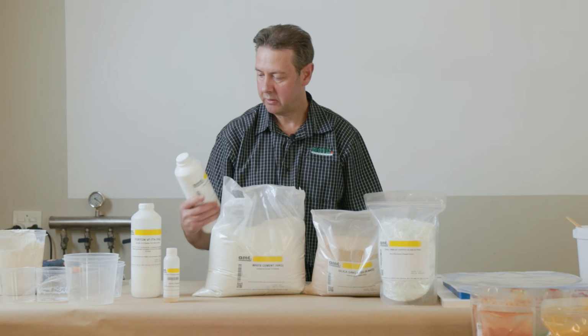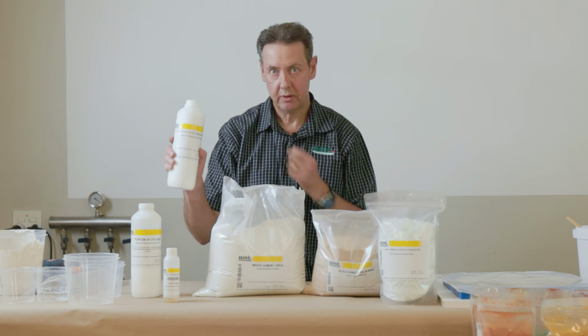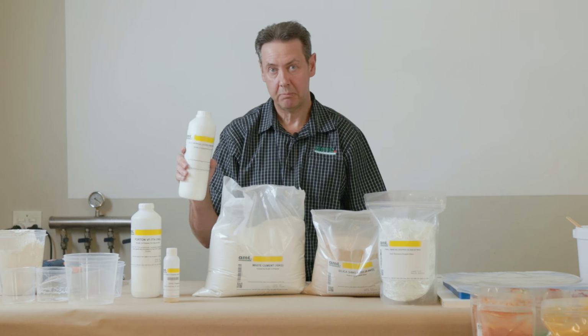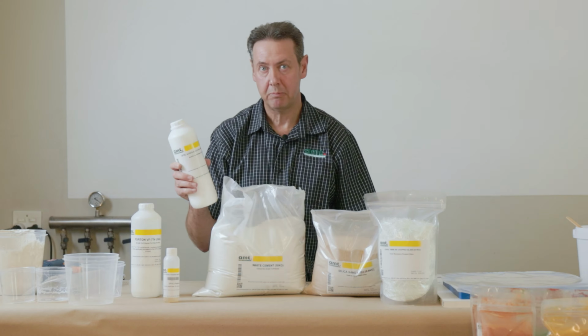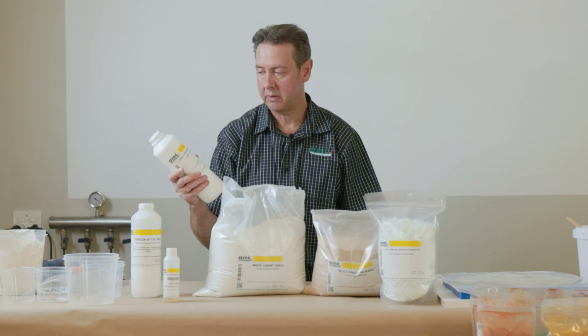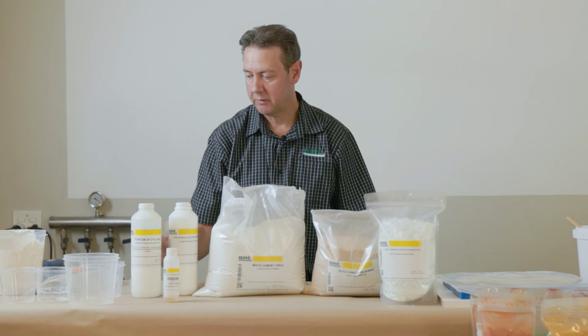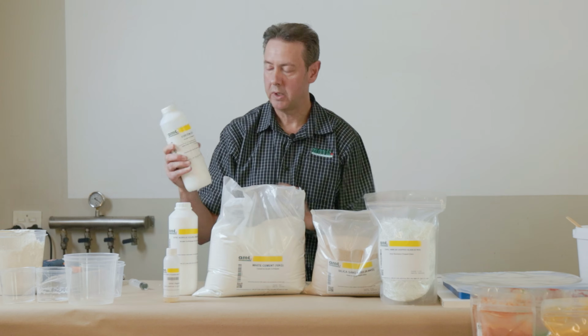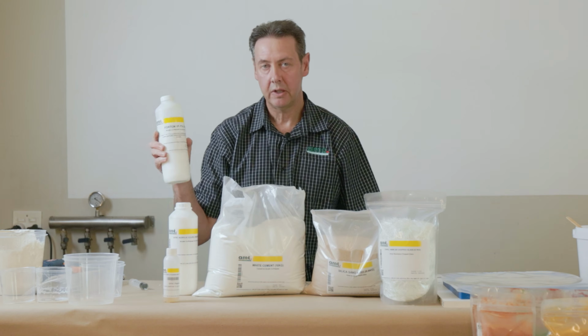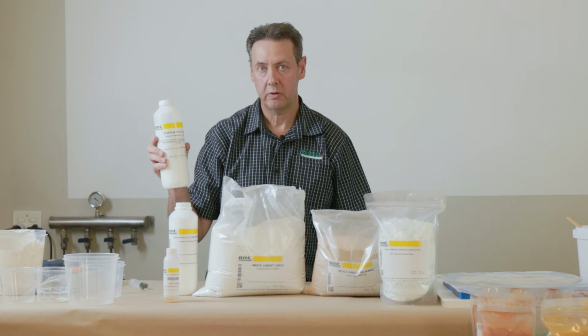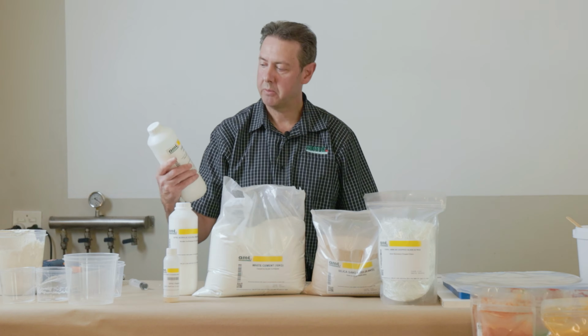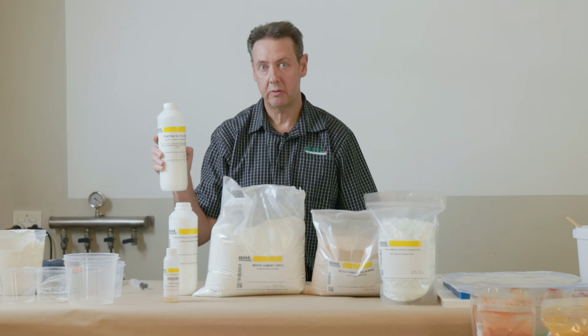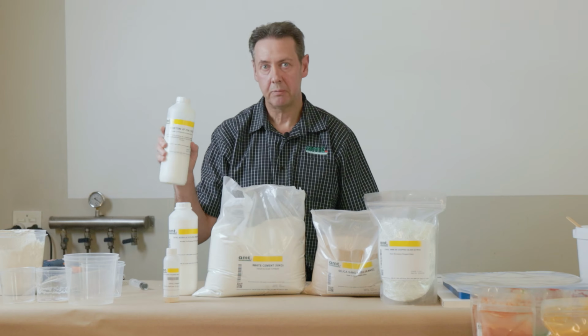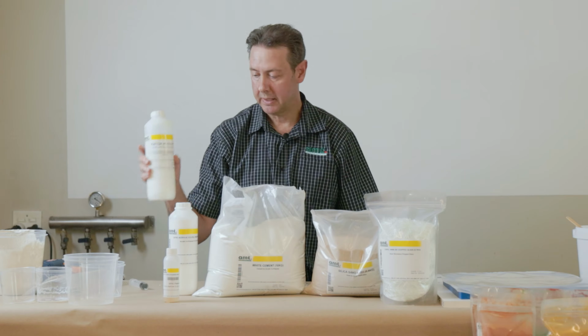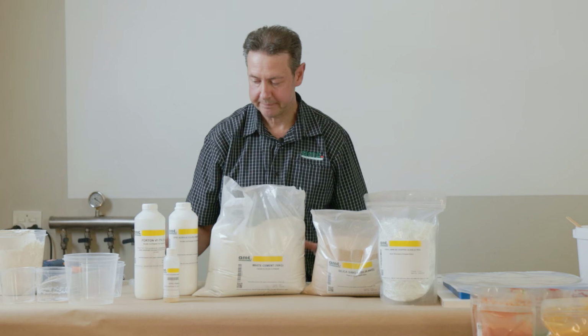And yeah, as I mentioned, the GFRC resin, I would probably stick to the 12% of the cement portion, which is 120 grams of this to the 1 kg cement. And if you're working with a Forton VF774, this has got a higher solid content. You can go in at 10% of the cement portion, which is going to be 100 grams to a kilo of cement, or you can also go up to 120 grams here if you need to as well. And that's our little starter kit.